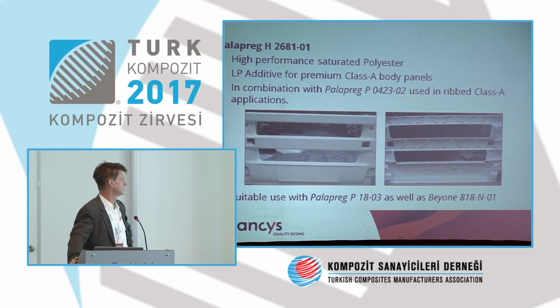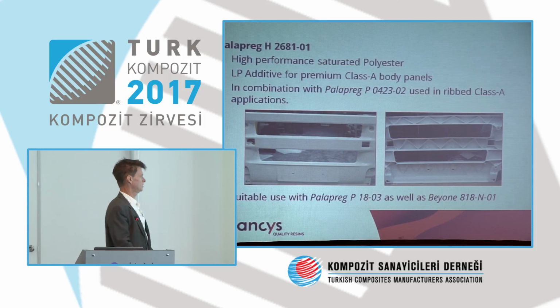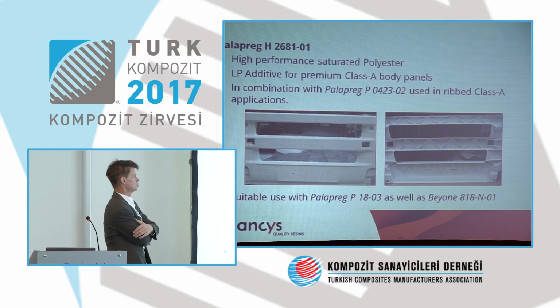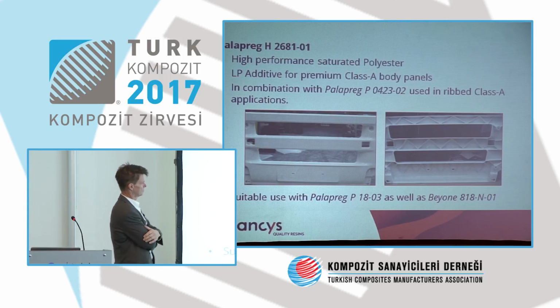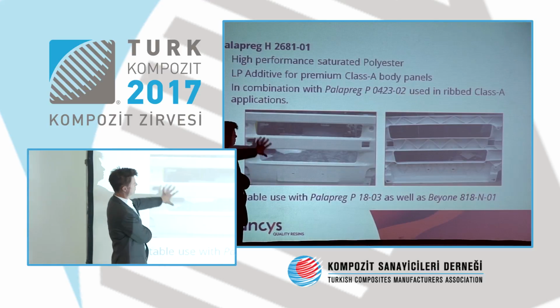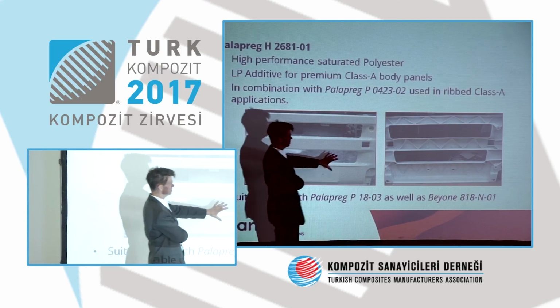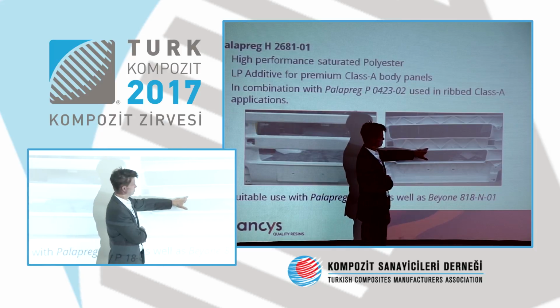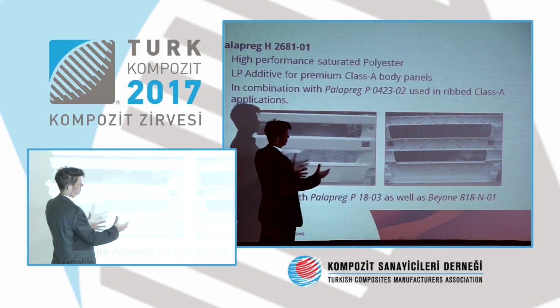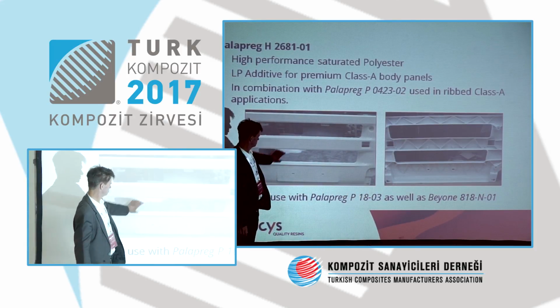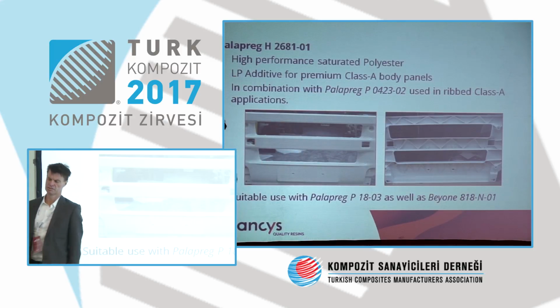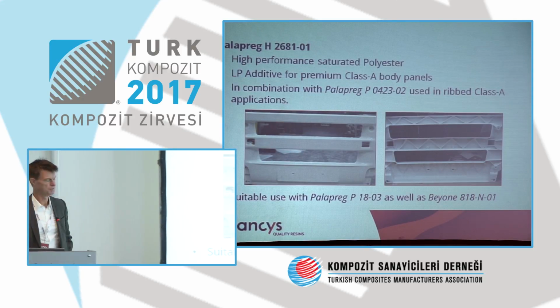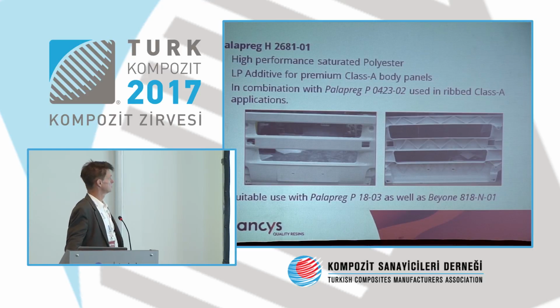Here, I give you also the example, because 2681 is the low profile additive, the best choice for rib panels. I just mentioned it before. This is a bumper, and there are the ribs behind and bosses. And this is at the end not any more visible. This is something really, really positive. And if you want to achieve this, the best choice is to start working with these materials in combination.